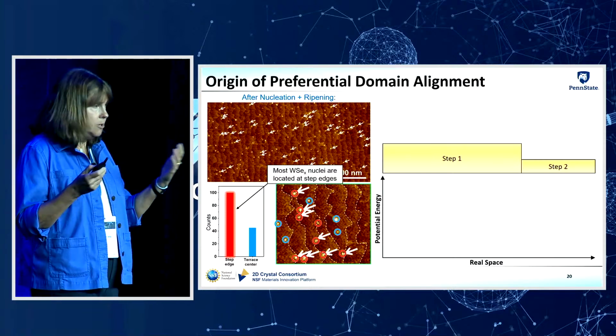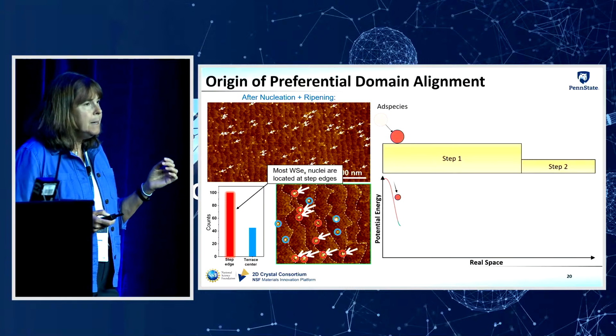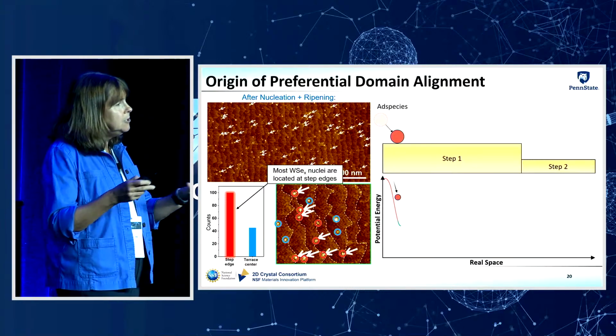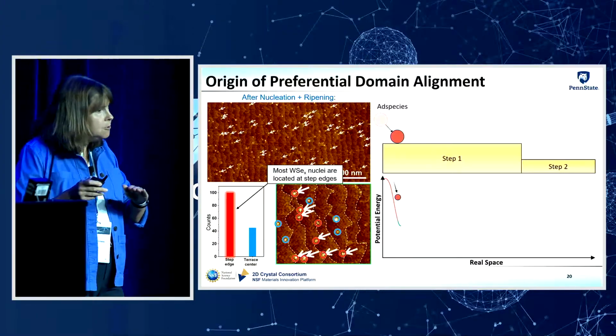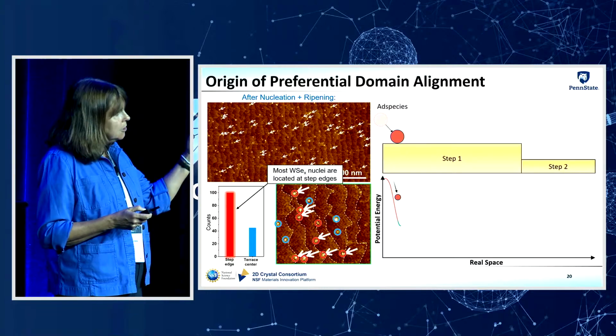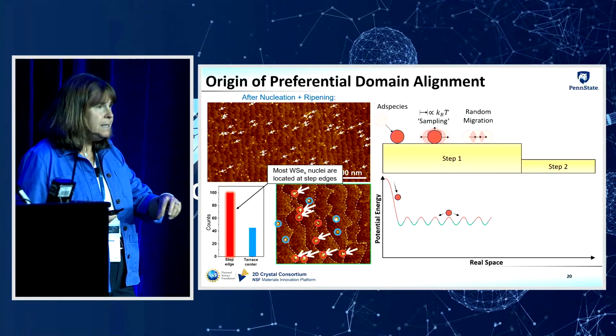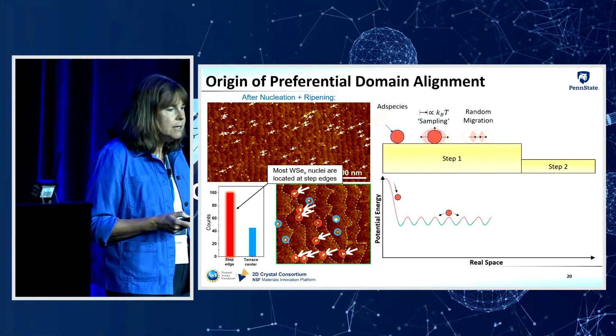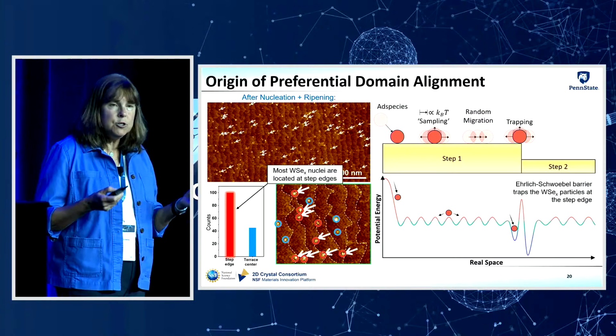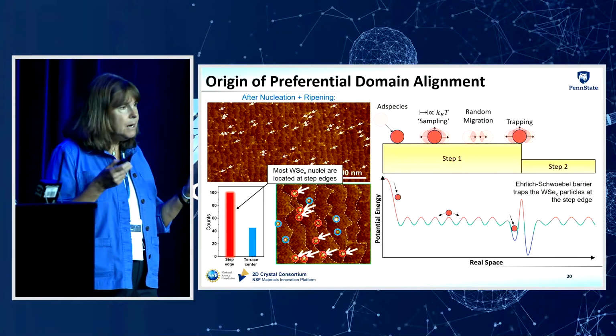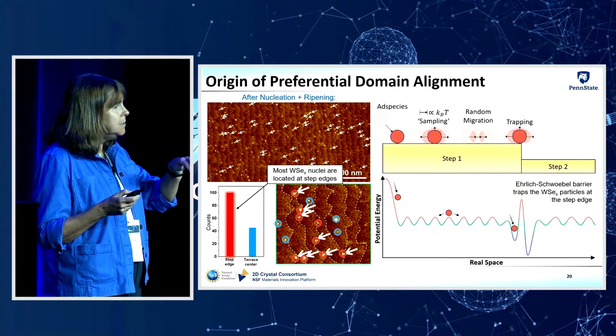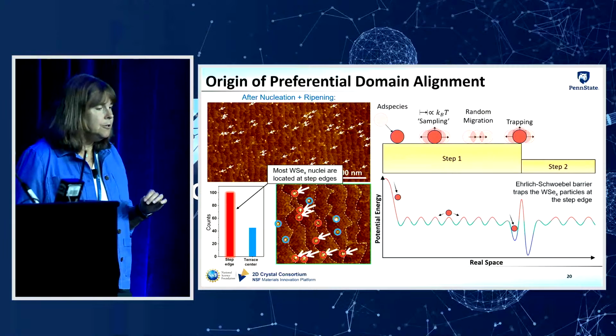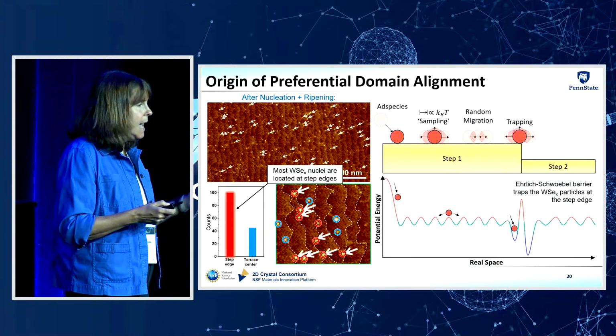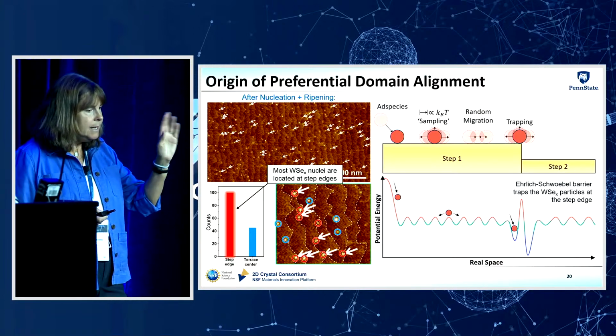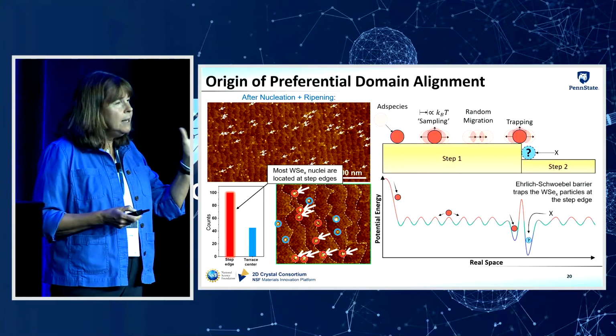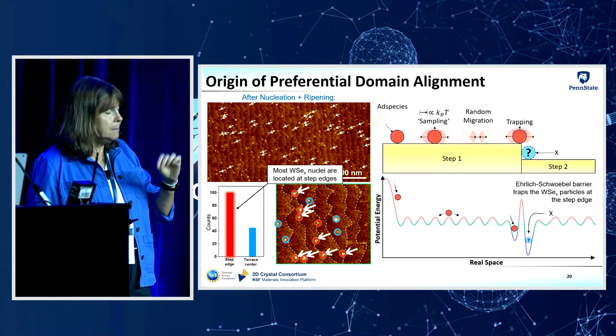And this is something that's not unexpected in epitaxy. If you just think about the fundamental mechanisms that occur and the potential energy landscape associated with diffusion on our step sapphire surface, you can see that we have adsorption occur, and then the adsorbed species can diffuse around on the surface, on the terrace, and then once they come to a step edge, they're going to get trapped by the Ehrlich-Schwoebel barrier. This is an energy barrier that exists anytime you have a discontinuity in the surface that you're using for epitaxy, and it can trap the atoms as they migrate across the surface. So they can get trapped at the top edge of the step, but the more energetically favorable location is for them to become trapped at the bottom edge of the step.